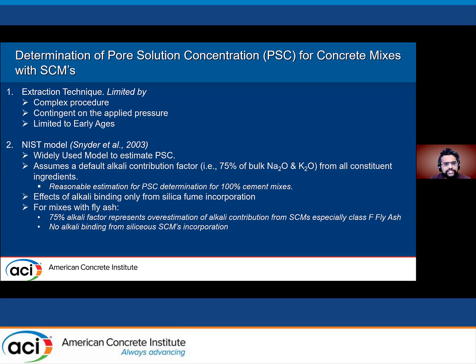Towards the modeling, the NIST model is one of the widely used approaches, but one of the things that the NIST model does is assume a default 75% alkali contribution from all its ingredient phases. If we remember our fly ash, cement, and fly ash composition, the 75% was the average contribution from cement, which appeared to match with cement. But for the fly ashes, it represents an overestimation, and this is moreover so for class F fly ash. Now, another thing the NIST model does is incorporate alkali binding from silica fume, but it does not take into consideration the alkali binding effects of, let's say, class F fly ash, which also is a significant source of amorphous silica.